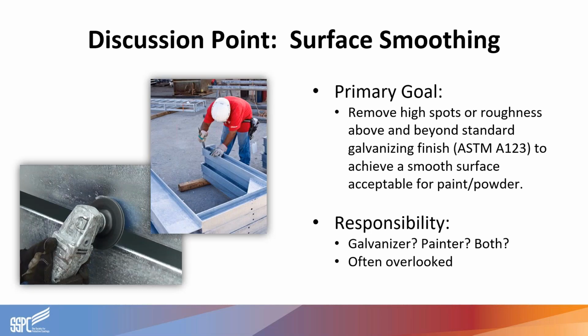Once any galvanizing repairs have been completed, the surface now must be smoothed before it is cleaned and profiled to remove those surface conditions I mentioned earlier that can impact adhesion. The primary goal here is just to remove any high spots, any roughness above and beyond the ASTM A123 standard galvanizing finish, to help us achieve a smooth enough surface that's going to be acceptable for the paint or powder coating. But who performs this? Is that the galvanizer? Is that the painter? Is it both? Often this particular step is the one that's most overlooked and left out of project bidding as well.